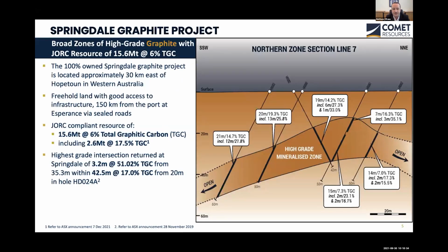Just looking at Springdale first and the resource there. What we have at Springdale is quite near surface, thick zones of graphite. We have a JORC compliant resource of 15.6 million tonnes at 6% total graphitic carbon. But the high grade zone of 2.6 million tonnes at 17.5% TGC is the area where the material has come from that we've tested recently. And it's that area of the deposit that has this quite unique, extremely fine, yet platy graphite. It was our interest in that and its potential to have battery anode applications that led us to do the metallurgical test work, which of course we released last week, and I'll go into that in more detail.